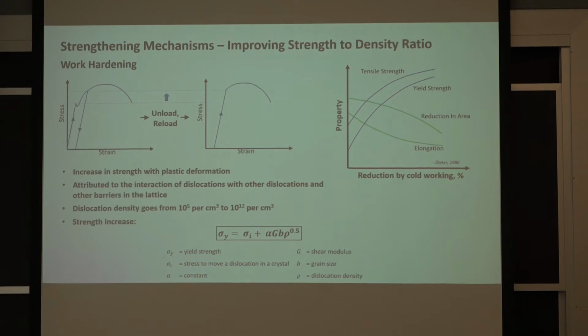So more dislocations, more tangling among one another, increase in yield strength. As they get stuck and jumble up in one another, they can't move, and effectively the material increases in strength. In fact, this is one model on how this increases, but some material scientists argue that the strength increases with the square root of the dislocation density.